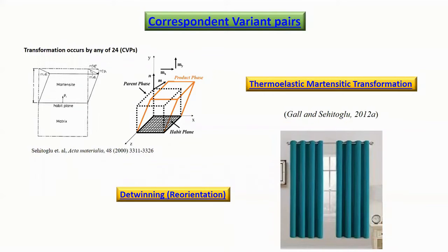Of course, there is not much enhancement in the stress in the process. So that is why we are going to see a plateau in the stress strain diagram. And that is how this entire thing is giving us a strain that can be recovered. So once we are unloading it, or we are adding the temperature, it is going back to the austenite phase. So it is going back to its unstretched form, the twinned one, and we can recover this amount of strain back.